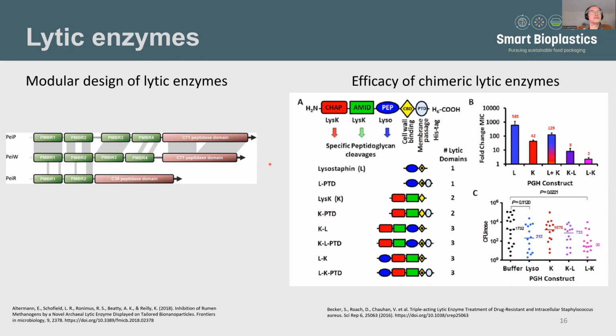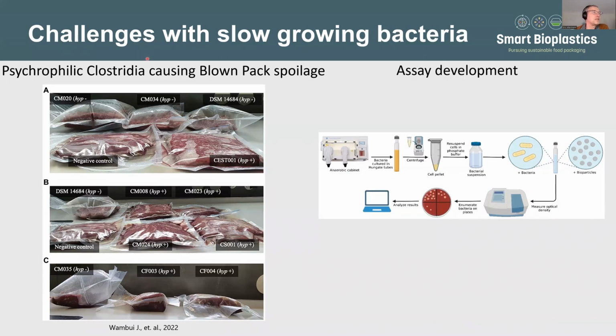And what we have found in our research so far is that if we are dealing with psychrophilic cold-loving bacteria such as Clostridia that cause the blown package spoilage, we run into problems, or challenges rather, in terms of how do we actually quantify the activity of those endolysin displaying bioparticles. And we found that because those Clostridia grow at, say, 4 degrees Celsius, we also slow down the activity of our enzymes. And in our assays, any background contamination has a tendency to take over. So it becomes very difficult to actually fully assess the activity of our functionalized bioparticles.